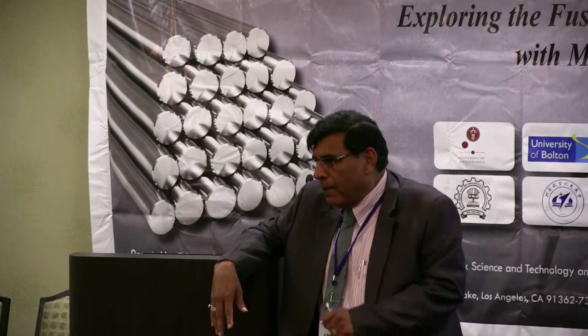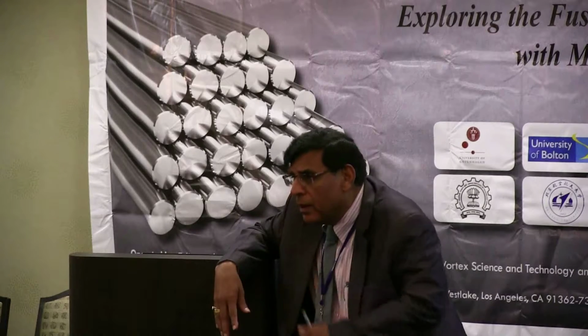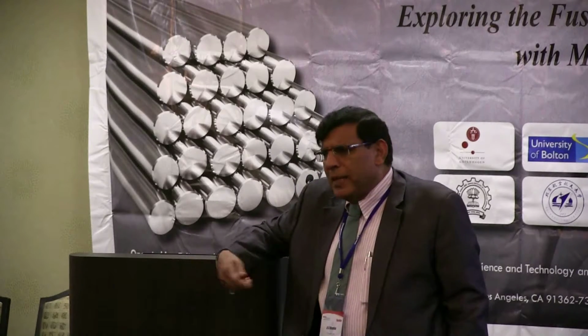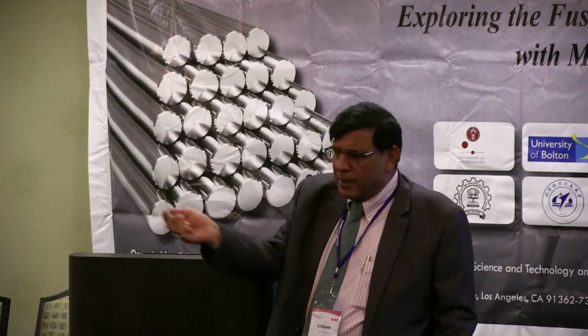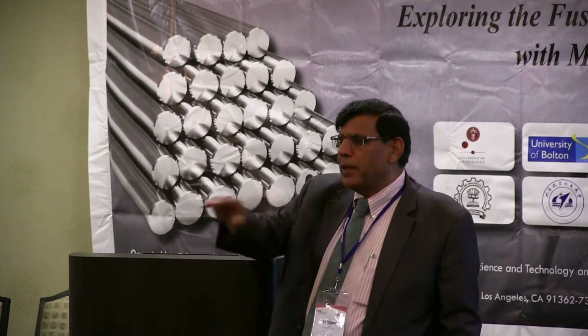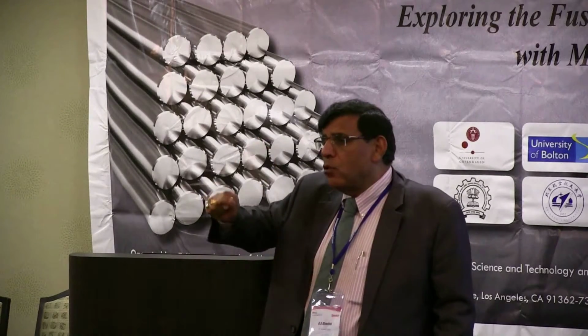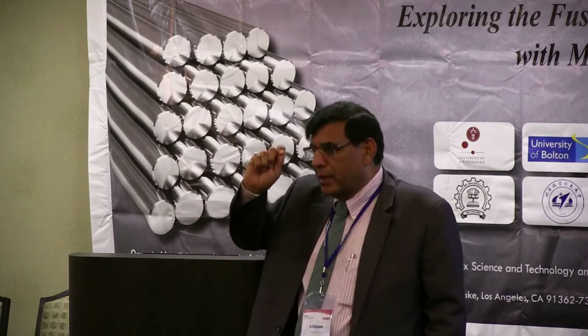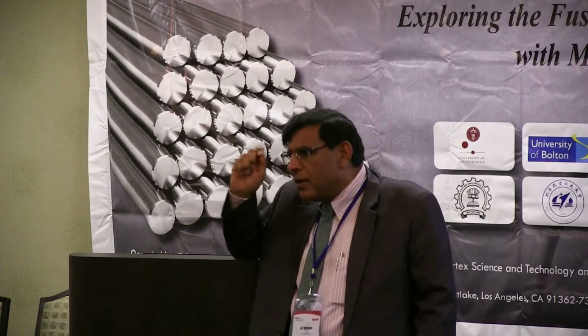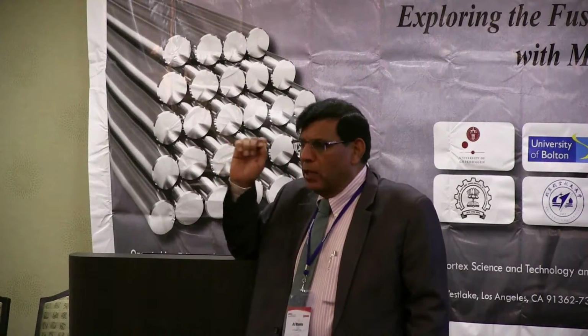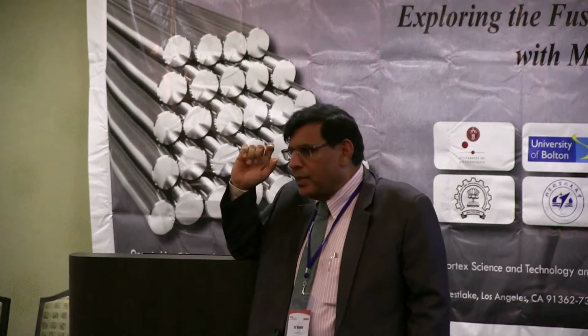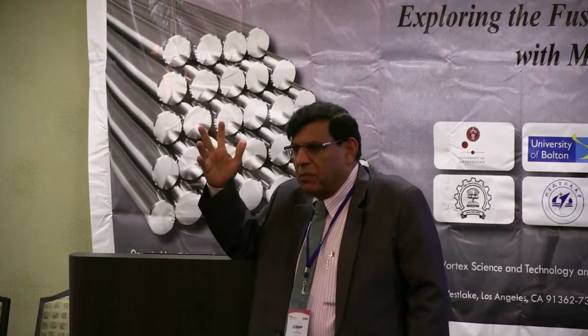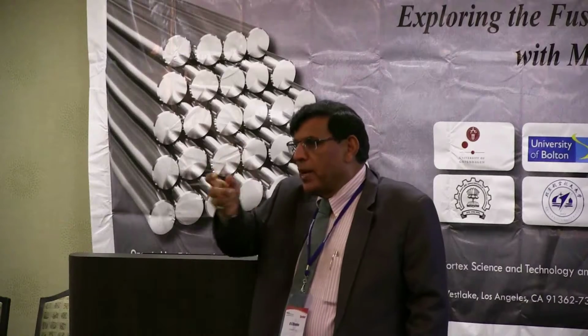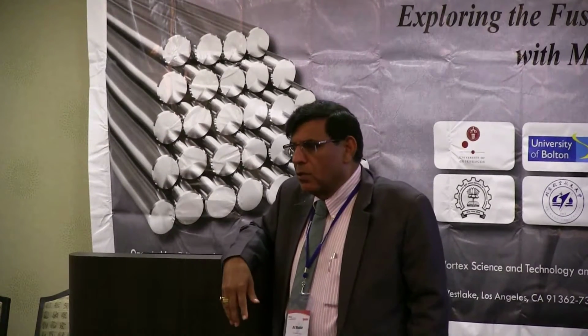And how do you coat the paper? Just paint it on? Normal spray method. Most of the things we have done by the normal spray method. The spin coating we use only for these lenses, because here we are looking at a very, very thin coating. You can see the coating thickness here is of the order of 100 nanometers or so, compared to several microns in the case of other things.